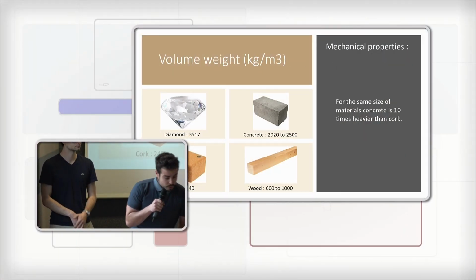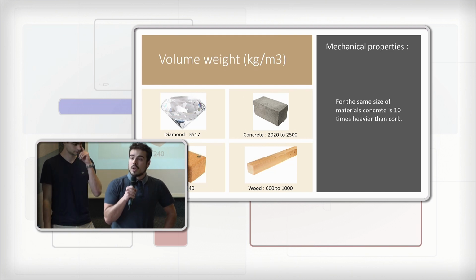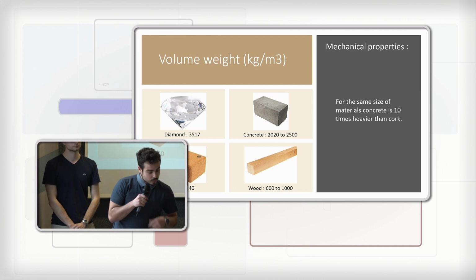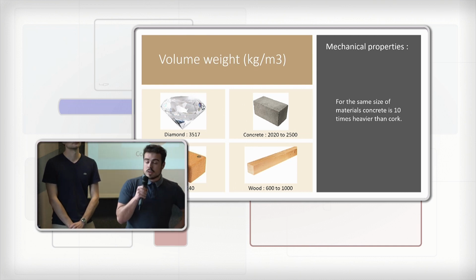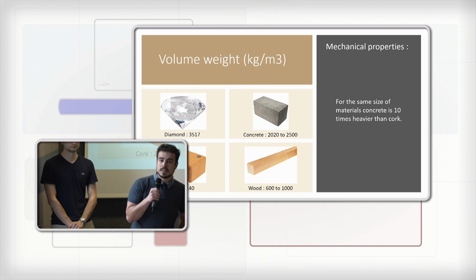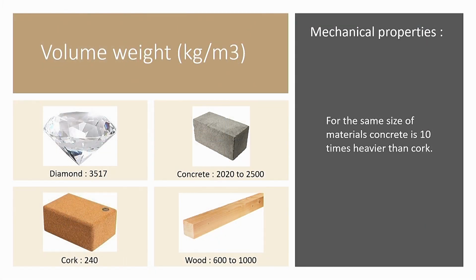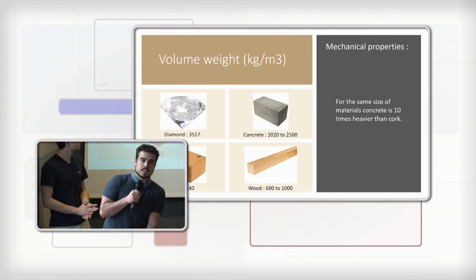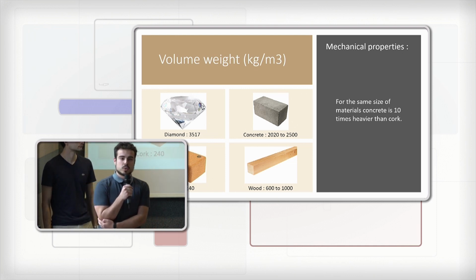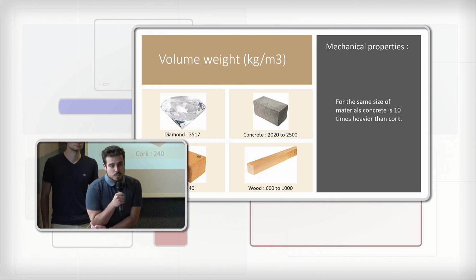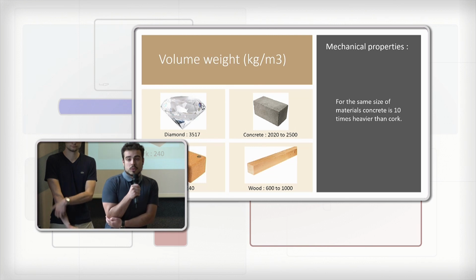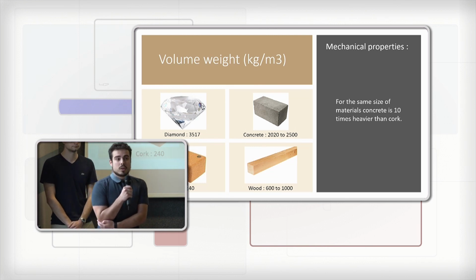We can discuss too the volume weight. So here you can see that the cork and the concrete do not have the same value. For the same size of material, the cork will be 10 times lighter than the concrete. It is an advantage because for transportation, it will be easier to transport cork than concrete. Another property of the concrete is that first it is a fluid, so it will easily fit the form that you want to have at the end. And it's a drawback for cork, maybe because you have a complex matrix of polymers. So this matrix will be hard to deform. If you want to have a liquid, for example, and then heat it, you can't because you will only degrade the material.